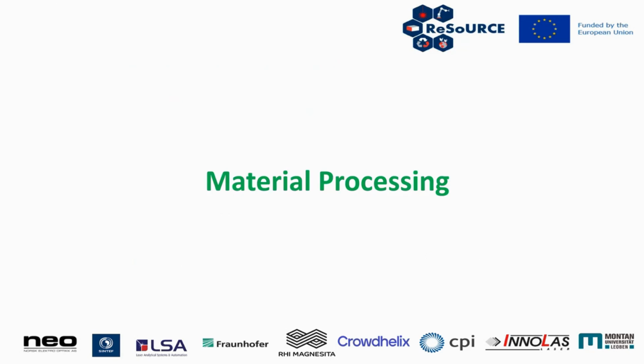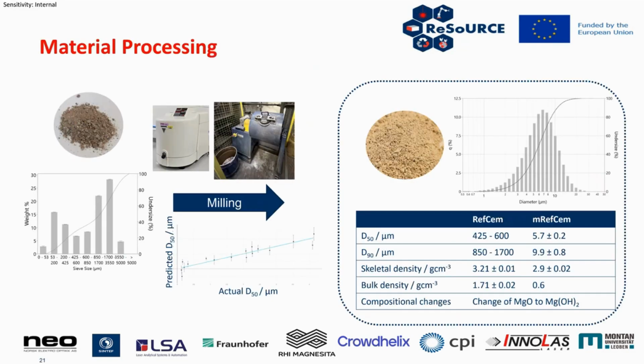So as these materials have a bimodal size distribution up to 5 millimeters, for certain applications, we realize that we need to do some processing of these materials to put them into applications. So for instance, to put into a polymer system, we need to process these materials down to a size class with a D50 below 10 micrometers. So we process these materials by milling.